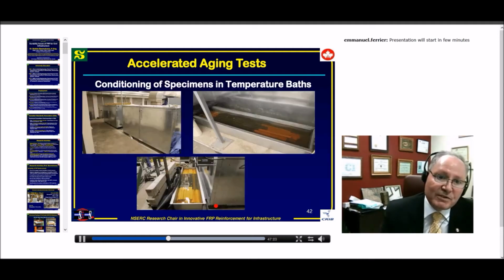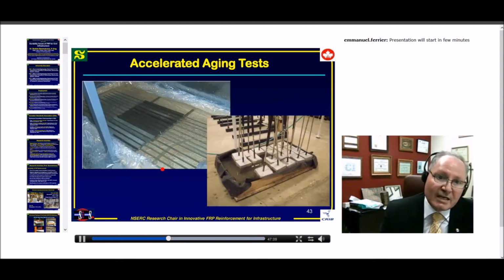This is what I showed you before: the bars or the FRP are directly immersed in alkaline solution. Sometimes, like here, the bars or FRP are embedded in concrete and placed in water, so we are directly using the concrete as the alkaline. Also here we have a bar in a concrete block, and this is mainly looking at the long-term bond and whether there is any degradation at the interface.